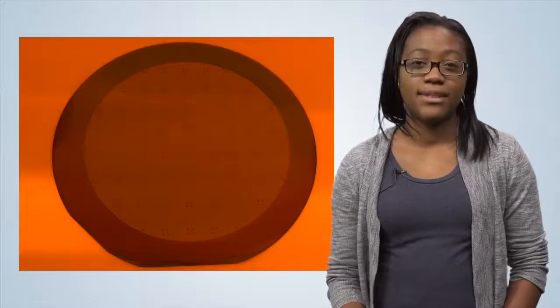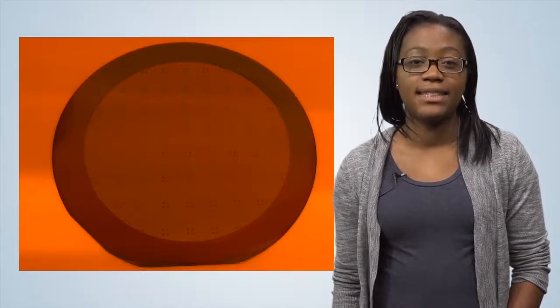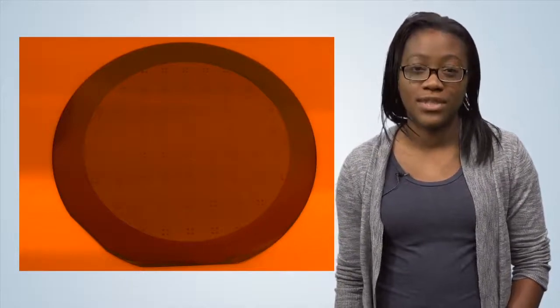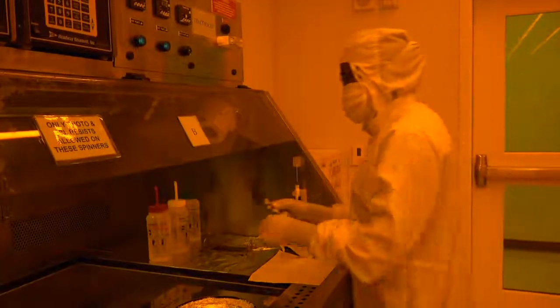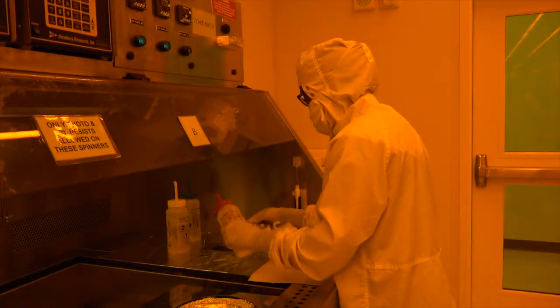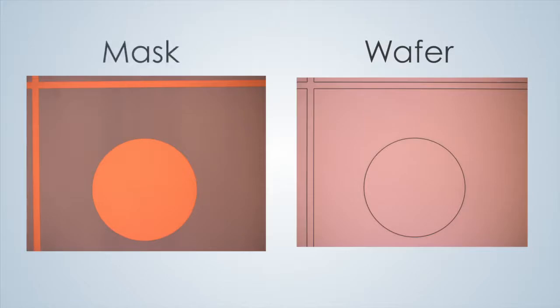Here's the etched sample. The silicon has been etched in the areas that were not protected by the photoresist. Let's remove the photoresist using an acetone solvent. Now, we can see that we have a copy of our photomask on the silicon wafer. Several microns of silicon have been etched away.